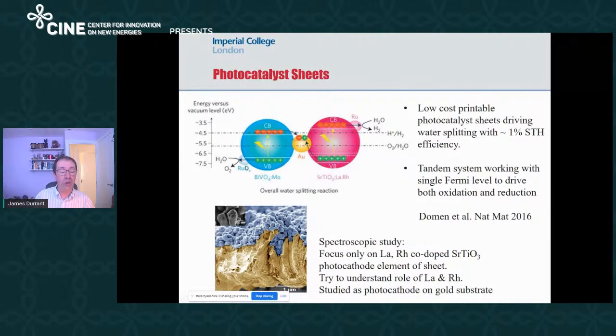So these are not photoanodes and photocathodes. These are sheets of a tandem structure based upon bismuth vanadate, essentially as the oxidation system, operating in tandem with strontium titanate as a reductant. And they've already been shown to be able to split water into hydrogen and oxygen with a 1% solar-to-hydrogen efficiency. And they're remarkably cheap. Essentially, you can screen print them. The interesting thing here, of course, is there's no applied potential.